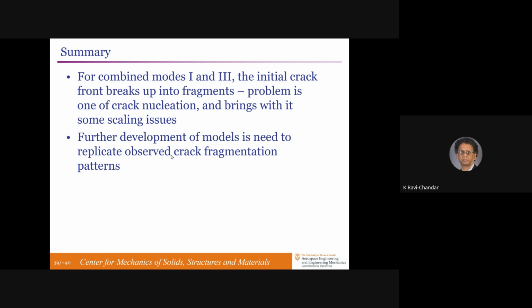Can these studies be useful for any manufacturing process of making complex structures? I'm not sure, but there is one thing that comes out almost immediately. The presence of a mode 3 increases the load that's necessary to crack it. The apparent fracture toughness will go up if you have a mode 3 superposed on it, because the cracks are no longer favorably oriented along mode 1, they're tilted. So if you had a part subjected to predominantly cyclic mode 1 loading, and you superpose a little bit of mode 3, it should decrease your crack growth, counterintuitively, if it is an elastic process. So there may be a strange technological application.